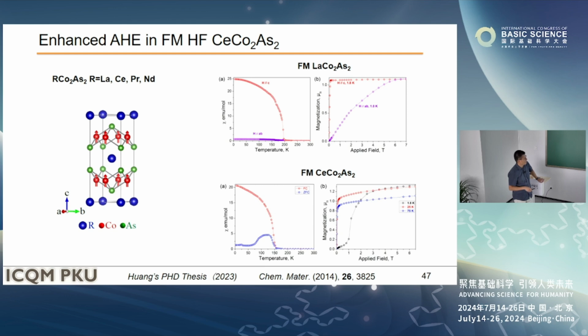And if we have a 4f1 like cerium in this compound 122, we find the TC is very close to the lanthanum compound, and the saturated magnetization is close to the lanthanum compound as well. This difference is much smaller than the expected ground state moment of the cerium 4f1 electron configuration, meaning the cerium 4f1 has been purely or nearly perfectly Kondo screened by the conduction electrons, so you cannot see the local moment of the cerium.